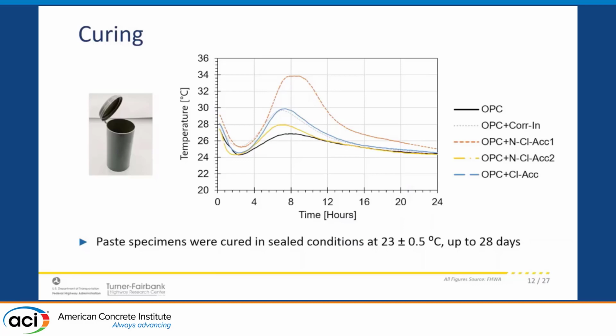The other factor that made us choose this type of curing was the fact that, based on a survey done among different DOTs, these type of repairs basically receive no curing. A lot of DOTs don't even apply a curing compound on the repair once it's cast. So seal condition was the type of curing that best replicated what was going on in the field.